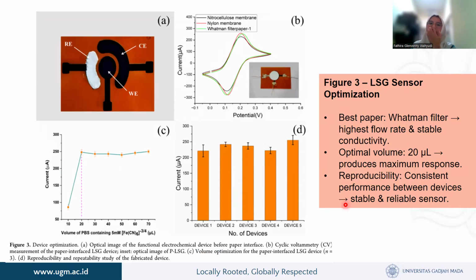I will move to figure 3, about the LSG sensor optimization. This is an optical photograph showing the LSG electrodes WE, CE, and RE that have been fitted with paper as an interface medium to hold the electrolyte solution sample. And in B, this is a cyclic voltammetry graph comparing three types of membranes: nitrocellulose membrane, nylon, and Whatman. The CV curve shows a characteristic redox shape, indicating good conductivity. Whatman filter paper produced the highest current and was selected as the best medium because it supports optimal ion diffusion.